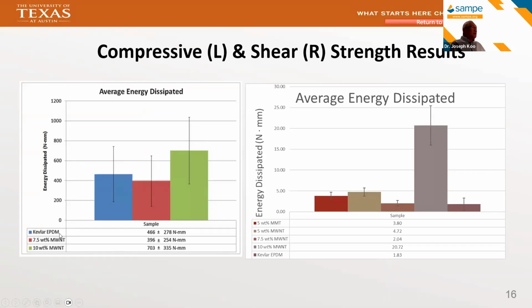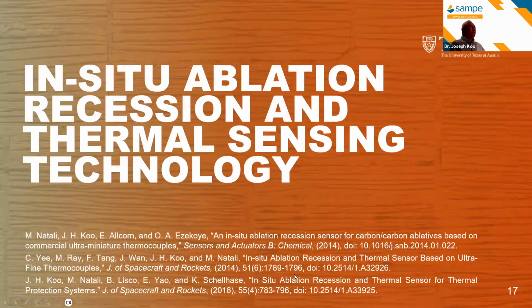So this is using Kevlar EPDM. This is a solid rocket motor insulation, and we were able to use a small amount of multi-wall carbon material, and we were able to see the average energy dissipated. This is how we quantify the strength in compression, as well as shear. So don't pay too much attention to the numbers. What I'm trying to convey to you is a methodology that we developed to understand why this material is working well. We were able to combine and correlate some of these data to performance. And this is what we have been doing, okay? Another area that we spend a fair amount of time on is to measure the in-situ ablation, recession, and thermal sensor.